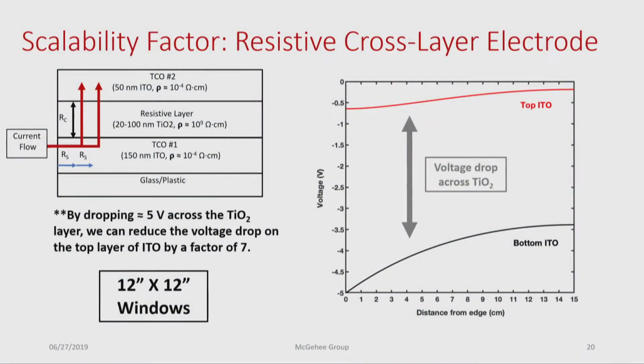So rather than trying to make a TCO with a much lower sheet resistance, we approach this problem from a different angle, by actually developing what we call a triple layer electrode. This triple layer electrode essentially has our two normal TCOs with a very resistive inner layer. When we apply a potential to our bottom TCO, since this material is much more conductive than the one above it, current will preferentially flow laterally rather than transversely, because current wants to flow through the path of least resistance.